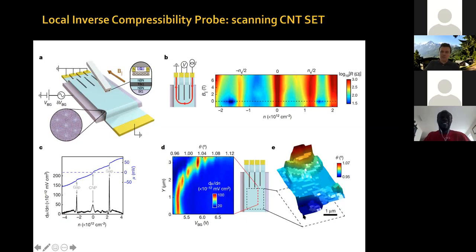So if you do this in a 2D map, you can take another map, similar to what I showed you yesterday for the scanning nanoSQUID, where we could get the spatial distribution of the twist angle. You can do it similarly with this technique. You can get spatial maps of the twist angle. Now, the sample turned out to be, for the most part, a little bit below the magic angle, but there are also regions closer, deeper into the magic angle.